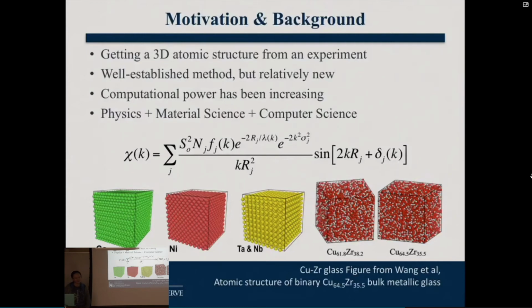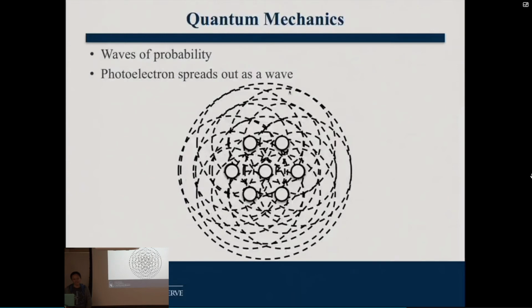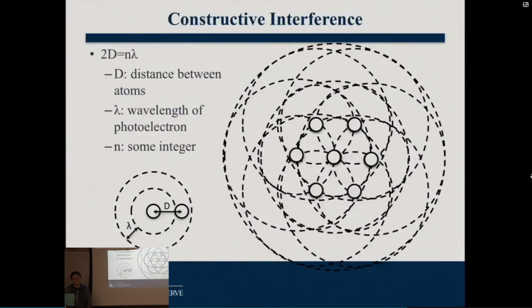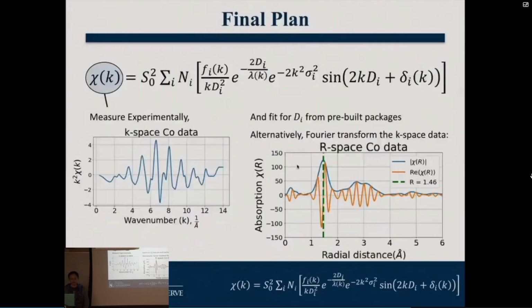I don't think it does that much. But you were showing the regularity and the constructive and destructive interference of the atoms. That would be harder to quantify in amorphous, wouldn't it? Yes, but what we're measuring here is the distance between two individual atoms. At the end of the day, after we sum our data, take the Fourier transform and fit the equation, this big peak here corresponds to the nearest neighbor distance.